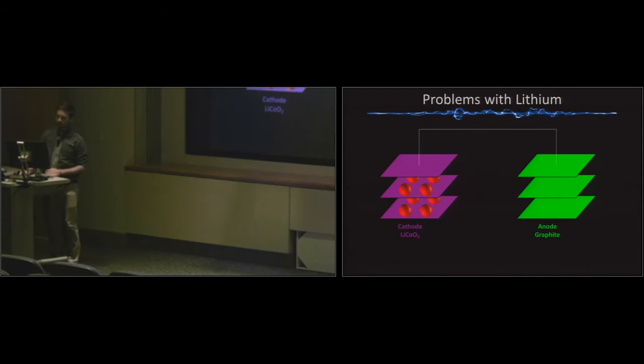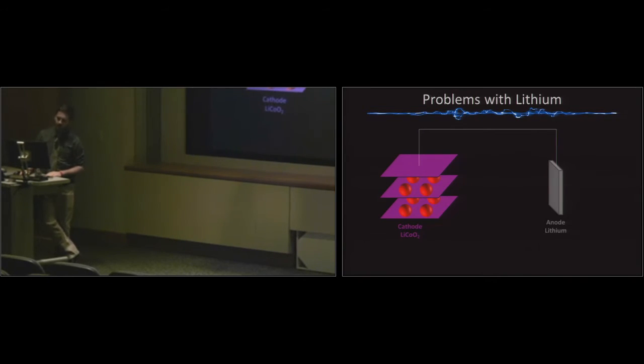So let's say we wanted to take our graphite anode and replace it with lithium metal. As we move the lithium over from the cathode to the anode, we would expect that lithium would have a nice, solid, smooth, flat plating going on. But in reality, it's not flat or smooth. We get these sort of long dendritic growths, and if one of these lithium growths touches the other side, you get a short circuit. Electrons pass rapidly between the two sides and heats up, and that can cause a fire